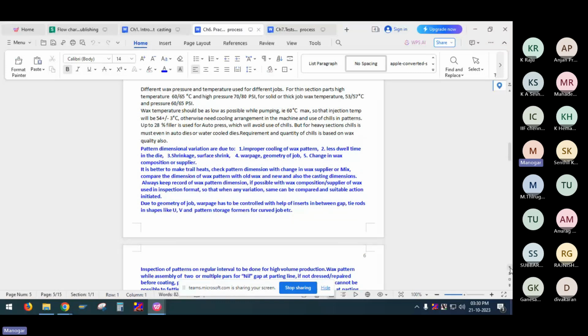And some of the points due to pattern wax, that is the wax pattern process, I'm just sharing. The pattern dimension variations are due to improper cooling of the wax pattern. See, after the injection, normally people put the pattern in water. Sometimes they do not, due to size or some other reason. Then also due to lesser dwell time based on the job. Then shrinkage and surface sink are due to high temperature of wax or not giving proper dwell time. Then warpage is due to geometry of the job or improper storage practice.